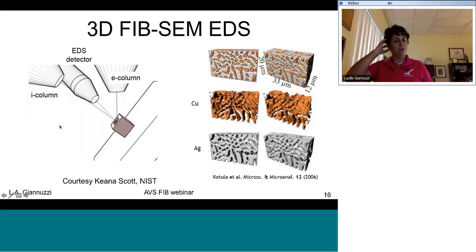You can also put other detectors into your FIB-SEM and therefore not only collect SEM images, but also different signals from either the SEM or the FIB, for example. So here was the first example of 3D FIB-SEM EDS by the group at Sandia. So this is a copper-silver material showing the differences there. So you have to, again, collect at each slice, you're collecting the EDS signal, and you're mapping that and then reconstructing the map.